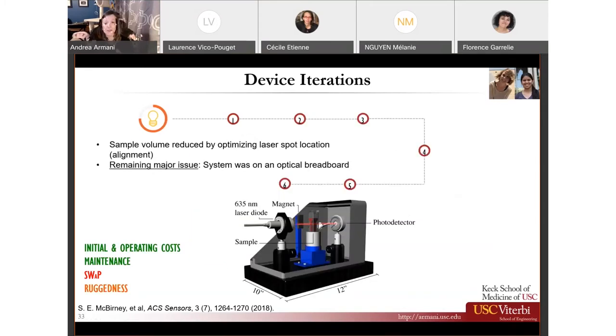So after many iterations, we were able to reduce the sample volume by optimizing the laser spot. We increased our detector size so that the alignment became incredibly simple because we had a large spot. We obviously had a remaining major issue in that this system was on a 10 by 12 breadboard, which wasn't really necessary because we were only mounting three optical components. So we didn't need a breadboard.